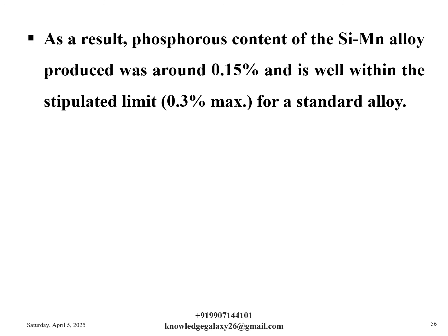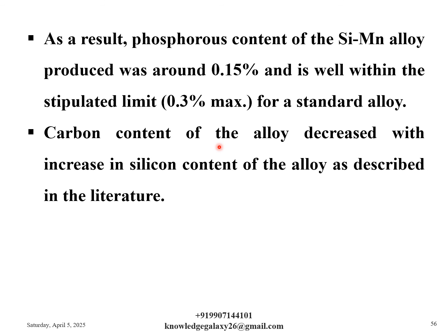As a result, phosphorus content of the silicomanganese alloy produced was around 0.15% and is well within the stipulated limit of 0.3% max for a standard alloy. Carbon content of the alloy decreased with increase in silicon content of the alloy, as described in the literature and as I have mentioned already previously.